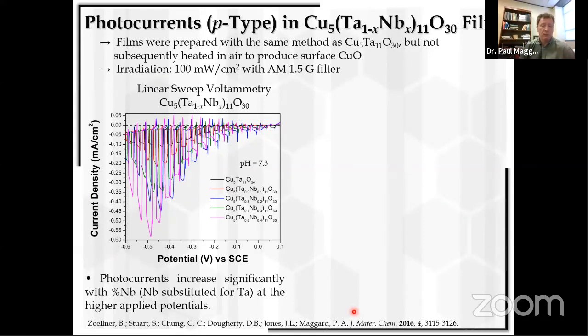Again, we made films of these and measured the photocurrents. And this time we measured them without heating them in air at all. And so in these cases, there's no copper oxide on the surface. What we see is we're putting more niobium into it. We're getting higher and higher photocurrents for this case, because we're absorbing a larger amount of the light. And as well, we're getting charge separation. We have to be, right? And the question would be why, right?